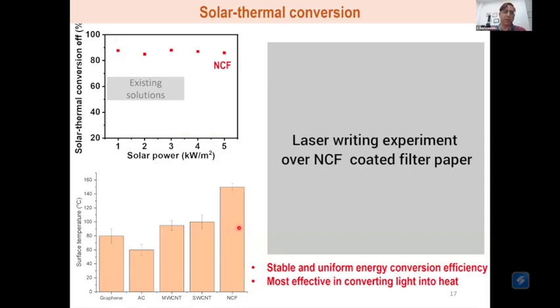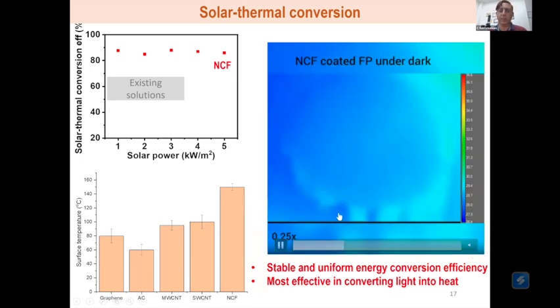And you can see that clearly from this kind of a graph where you have mapped graphene, activated carbon, different allotropes of carbon, and NCF being the material that we have made is actually one of the highest surface temperatures, yields one of the highest surface temperatures. And this is also captured in this short movie that I'm going to show you, which is basically a thermal movie. This is captured using a thermal camera.